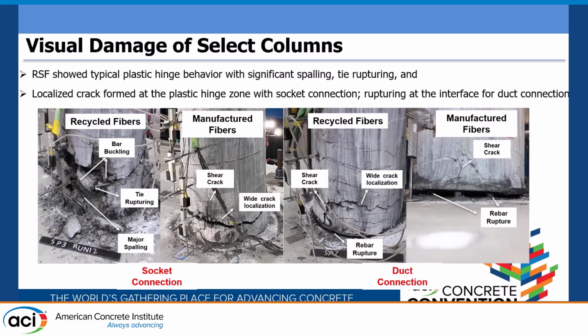Okay, so this is the visual damage that we had. We saw that the recycled fiber did a very good job in the plastic hinge. We saw a lot of damage, but we still see some of the spalls still attached because of the fiber. They're very good at the macro level at holding the cracks in. But a pretty typical failure: we saw bar buckling, tie rupturing, and also some major spalling.